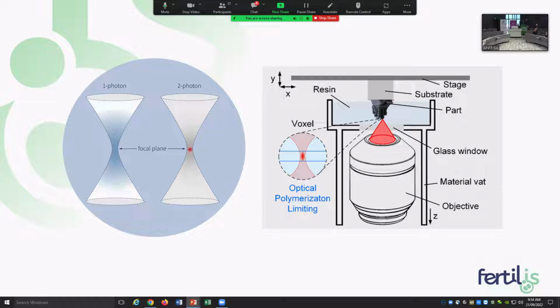Two-photon polymerization 3D printing solves these challenges. So what's 2PP? It's based on two-photon absorption, 2PA. Essentially this is a nonlinear optical process, and what it does is it reduces the amount that is polymerized by the laser. So we use photosensitive material and a laser, and that polymerizes right at the focal point. So unlike one photon, 2PA gives us really, really small nano building blocks, which we can then use to build up a very precise structure.